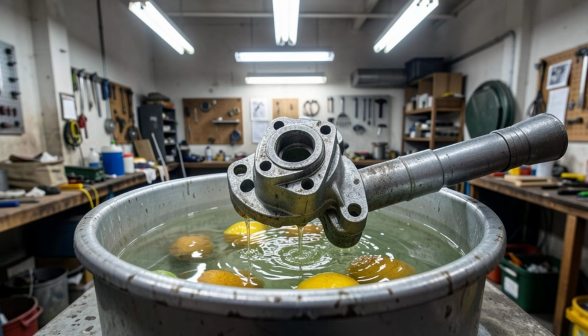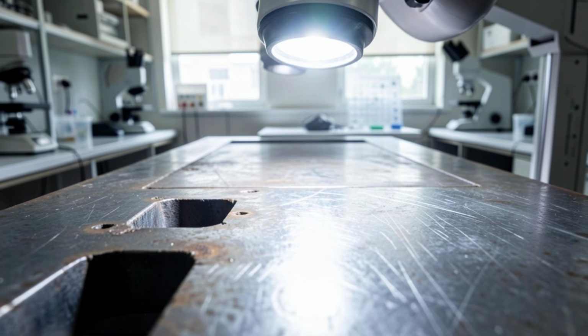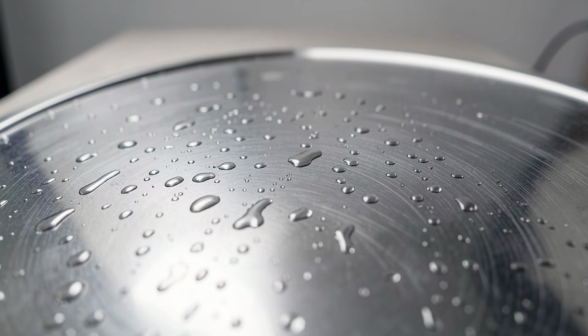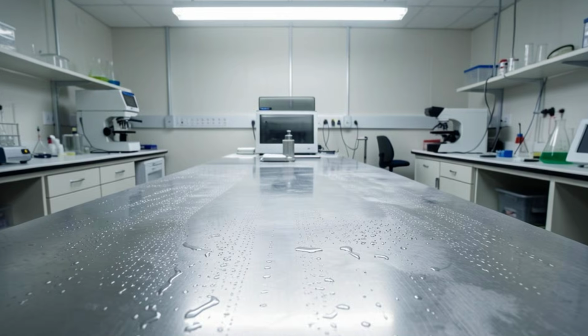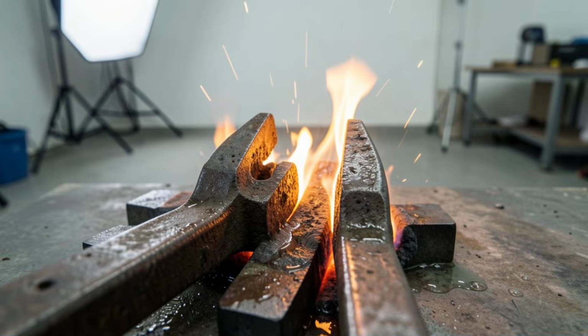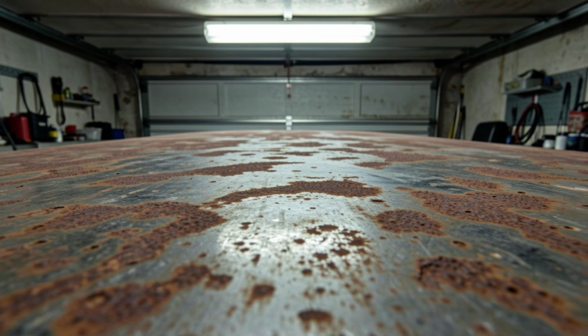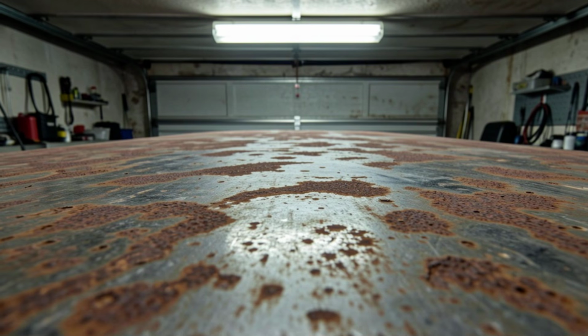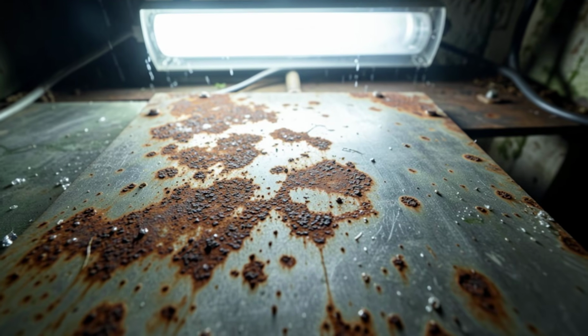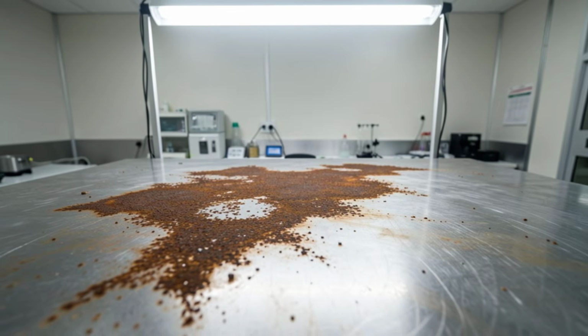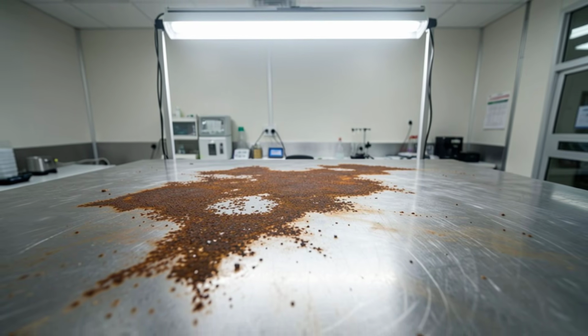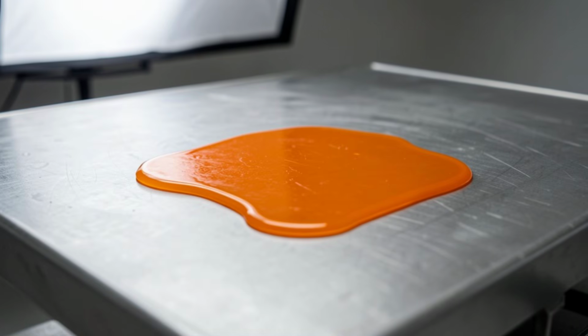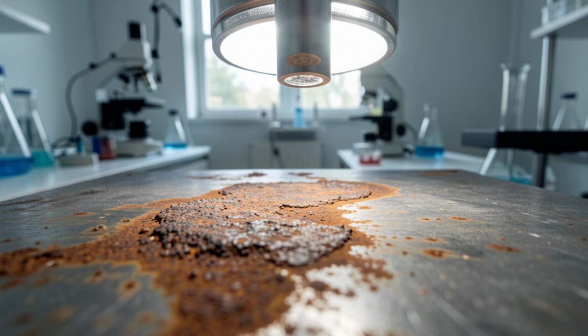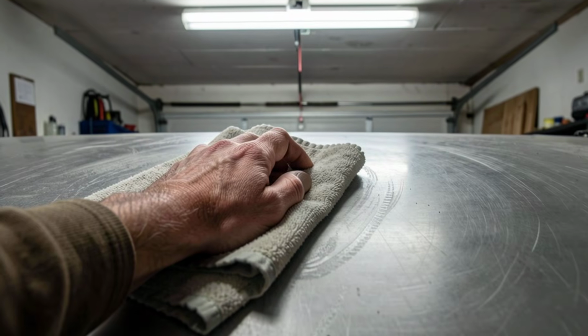What you have when that part comes out of the bath is the most exposed, reactive steel surface that part has ever had. It is atomically clean iron in direct contact with air and humidity, and iron in that state will react with the oxygen in the air and the residual moisture on the surface, and it will begin to rust again immediately. Not in an hour, not overnight, in minutes. Sometimes in under 2 minutes, depending on your garage humidity.